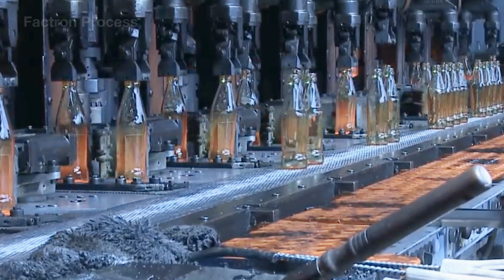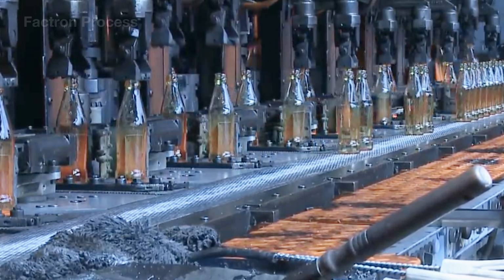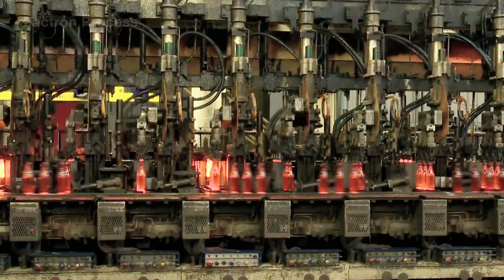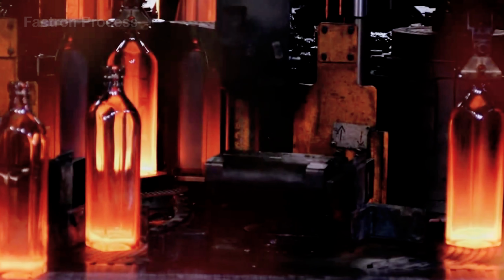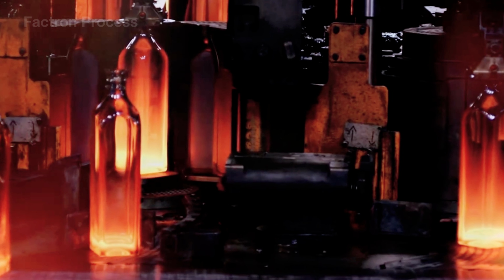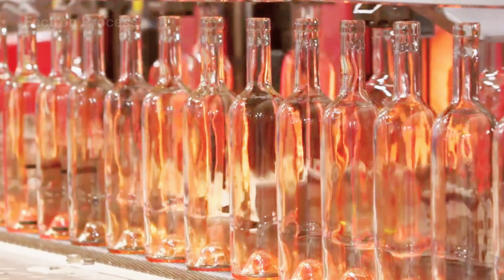At this point, the pieces of glass that once lay in the trash have taken on a new form, but the product that has just left the mold is still very hot and contains a lot of internal stress. Therefore, it must go through an annealing lehr for controlled cooling.